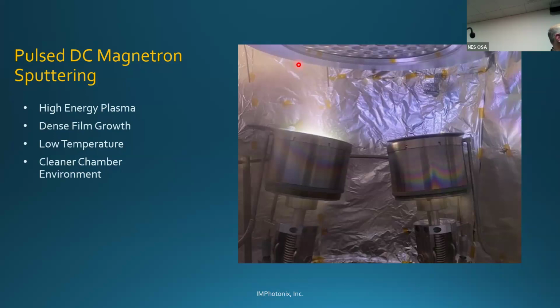Yeah, most of the time we're dealing with very thick substrates. In our case, we're a quarter inch, 10 millimeter thick substrates, and so we don't hear a lot about deformation of the substrate due to the stress of the film. I do know that if you're working with laser mirrors that are 20th wave and you put a 25 layer high reflector coating on it, that 20th wave is probably going to be 8th wave when you're done. So that will affect that. And if the substrate was very thin, yes, I'm sure it's going to affect that.